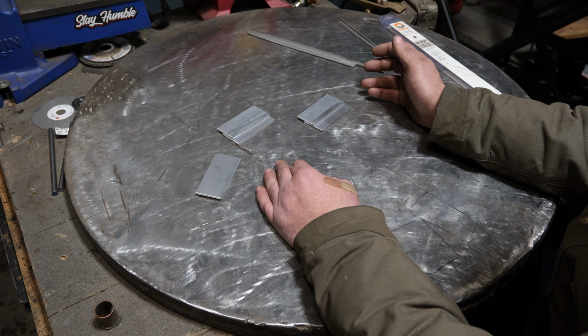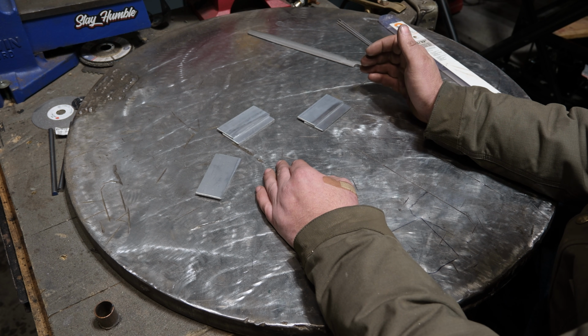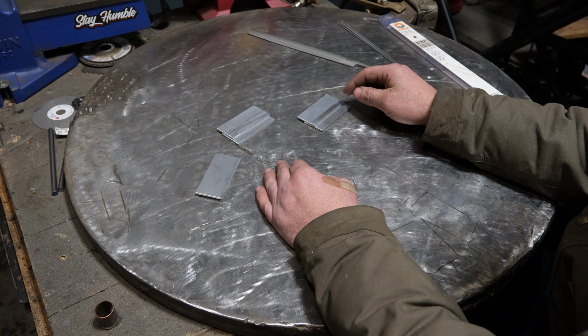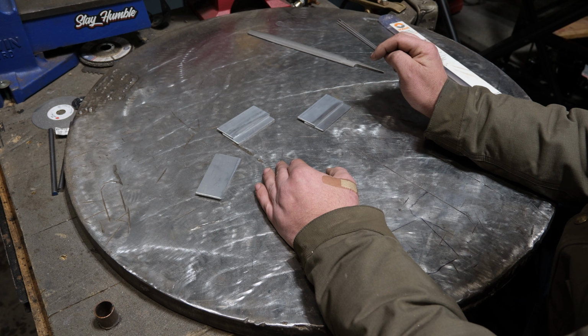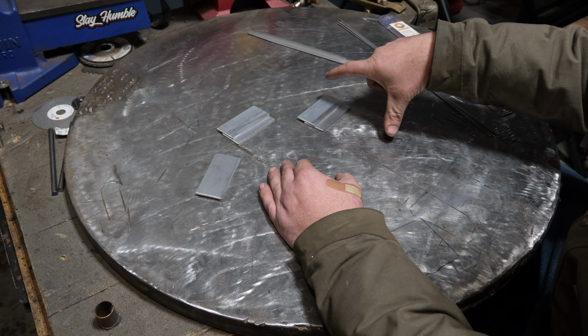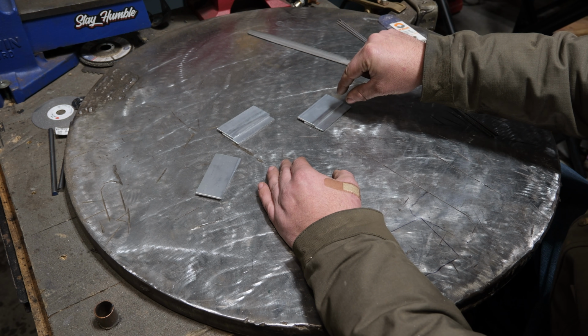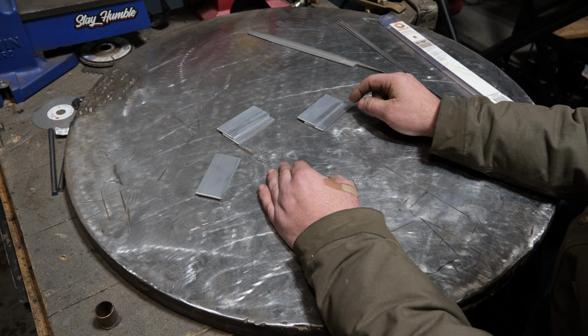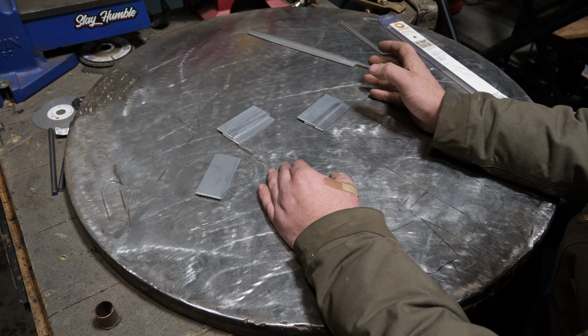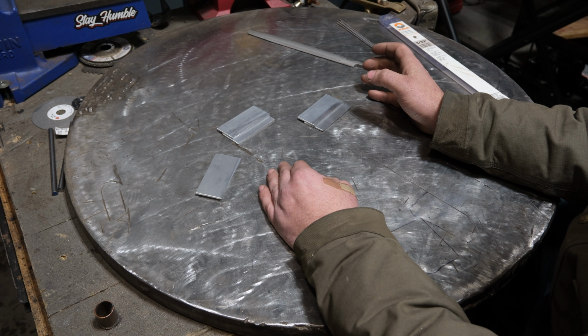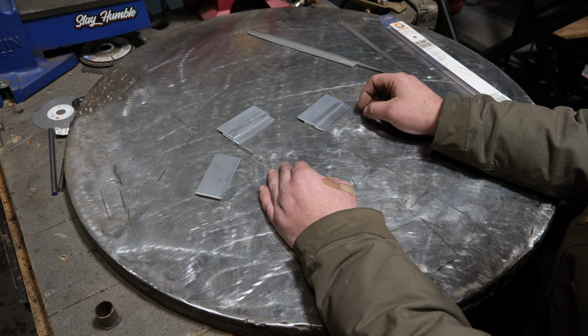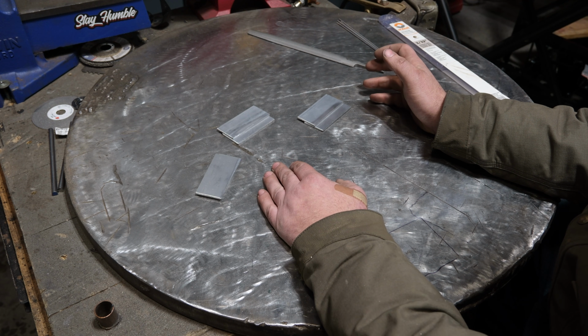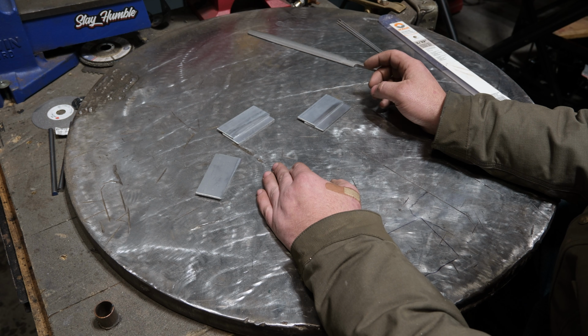The downside with AC TIG is that it limits penetration significantly. Well, with DC, you have 100% negative, and all of the penetration exists on the negative, not to mention it necks down the weld pool significantly over AC, so you have much higher heat input in a much smaller location, plus the added boost of much higher voltage due to the helium. That gives you the ability with a 200 amp TIG welder on DC to weld absurdly thick, like 1-inch thick aluminum with massive penetration.